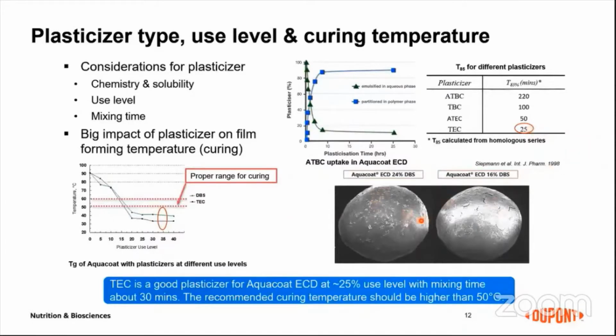And also we can see the impact of plasticizer use level on the film layer quality. Here from the SEM picture, we can see we have enough DBS as plasticizer. On the left side, we can have a very smooth and continuous film layer. But if we add insufficient DBS plasticizer, there are some cracks on the film surface. So basically, this is kind of a high risk for the drug release control. So it's significant coating defects on the film, right?